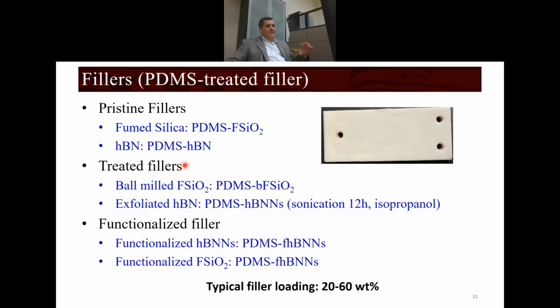We also did two different kinds of treatment, a physical treatment, like ball milling and exfoliation, without adding any chemicals. For the ball milling of the silica itself, it is an attempt to reduce the particle size of the silica and try to reach the nano range, hopefully. Also the exfoliation: the hBN is more like sheets, so we are trying to exfoliate these sheets using sonication and isopropanol. And another effort is going on to functionalize the silica itself. Typical loadings we use are from 20 to 60, and this is an actual sample with the filler and the PDMS.